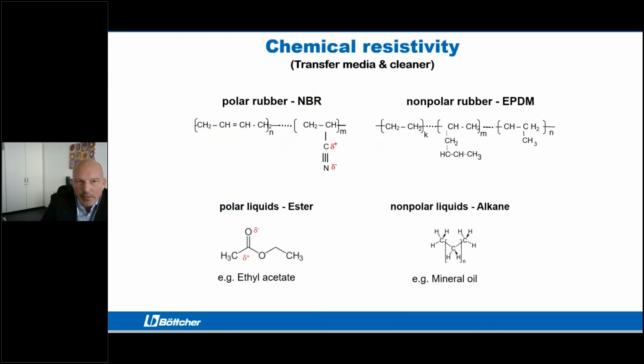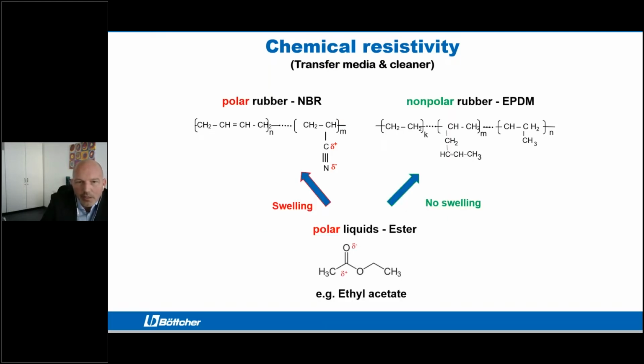When it comes to chemical resistivity, just some simple, we split in polar rubber and non-polar rubber, and also in polar or non-polar liquids. If you have a polar rubber like NBR, for example, and you have a polar liquid like an ester, like ethyl acetate, and you put it together, you will get a swelling. If you combine an EPDM, for example, with a polar liquid like ethyl acetate, there is no swelling.